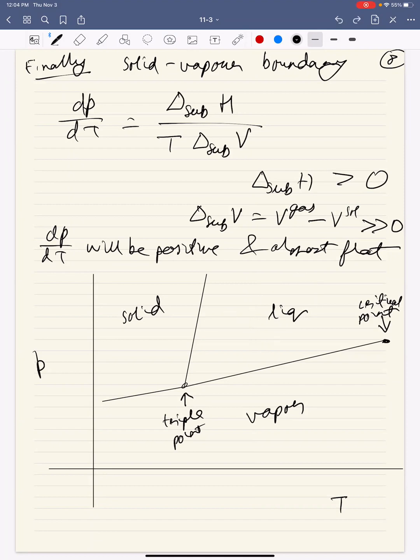If you go and look up, I recommend all of you to go look up the water phase diagram. You will see how the solid is actually a whole jungle. It really splits into complicated geometries. It starts to look almost like the iron carbon phase diagram. But this is always true. Any single component system can at max have a triple point. This does not mean a single component system can have only 3 phases. It can have 500,000 phases. At the same pressure and temperature, at best, you can have 3 of them coexisting.